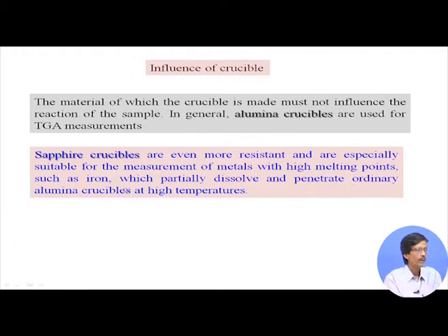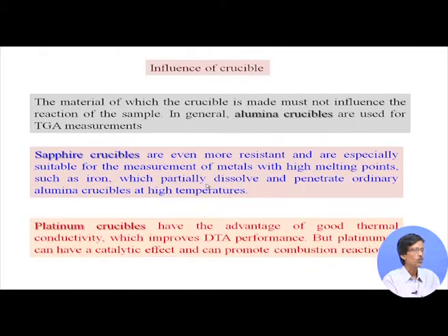If we take iron, some amount of alumina can be consumed, that means after some time of use the alumina crucibles will be corroded, and sometimes iron penetrates the alumina crucible at high temperature, if the material has not been made nicely, because the surface texture is very important; the surface should be resistant to reacting with the iron samples. So, this is one form of crucible we can use in preference to alumina crucibles.